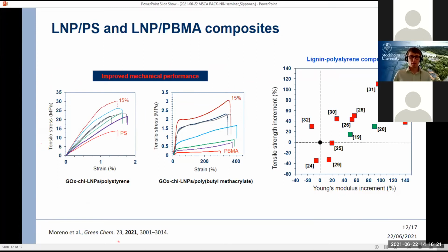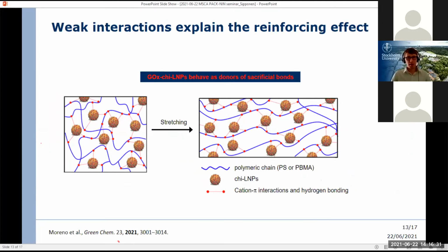And in case of the polystyrene, we found that the increase in the tensile properties was basically highest that has been reported. So what is the reason for this? We believe it is dynamic sacrificial bonds that are forming. So these are covalent linkages that form between the polymers and the particles. So when we have the polymer matrix, these particles act as kind of nanospacers, which enable the stretching of the material and then also make it more elastic, while also giving some improvement in the strength.